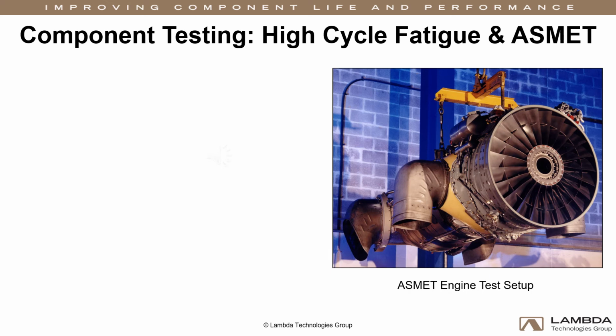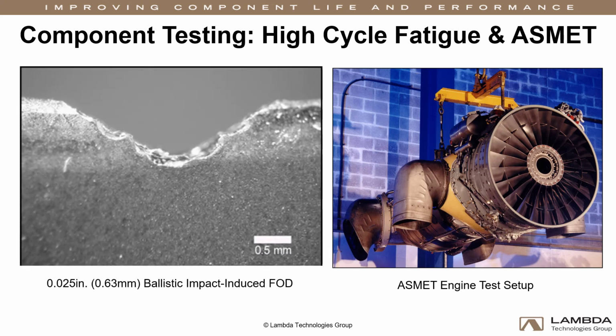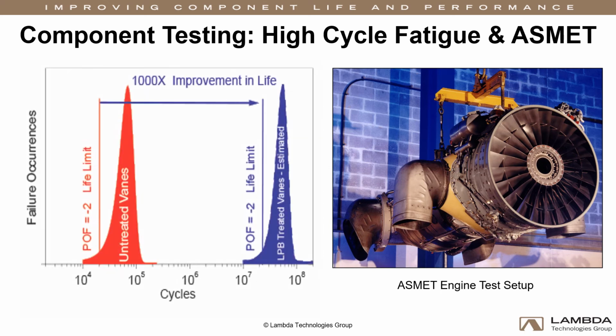Engine testing by the OEM proved that LPB resulted in complete mitigation up to 0.025-inch, or 0.63 millimeter, deep FOD introduced by ballistic impact at the trailing edge failure location. This was reported to be the first time deliberately damaged airfoils were ever subjected to an engine test because of the risk of complete engine failure. LPB produced through thickness compression in the critical vane edge, completely inhibiting crack propagation.